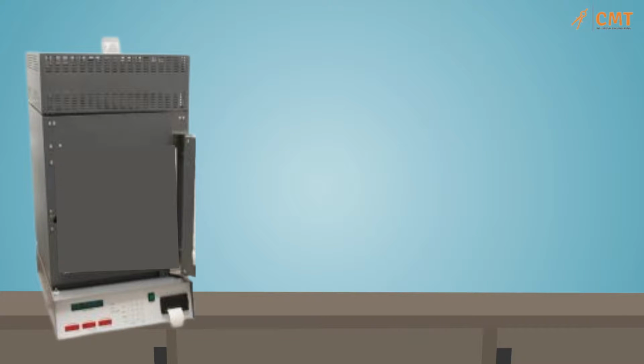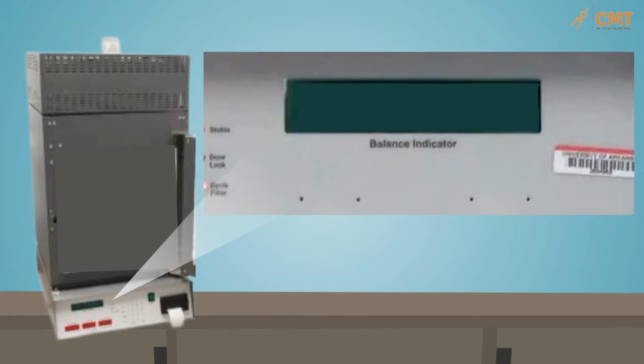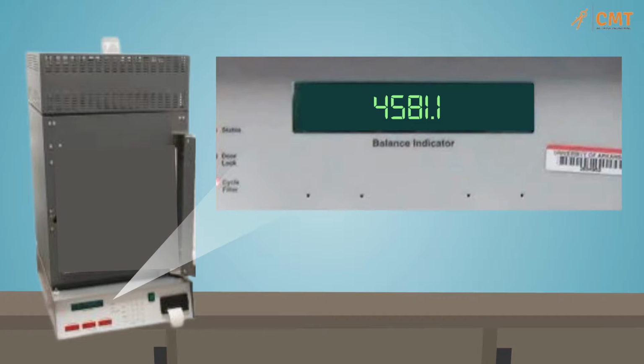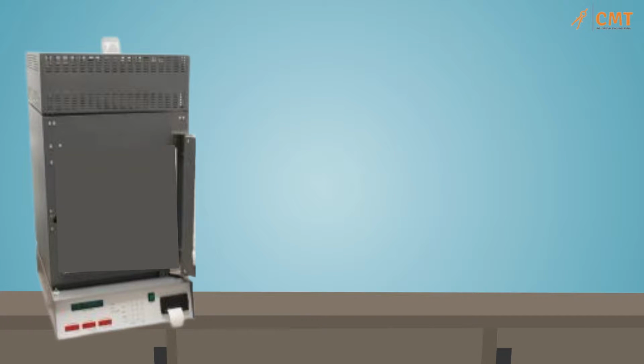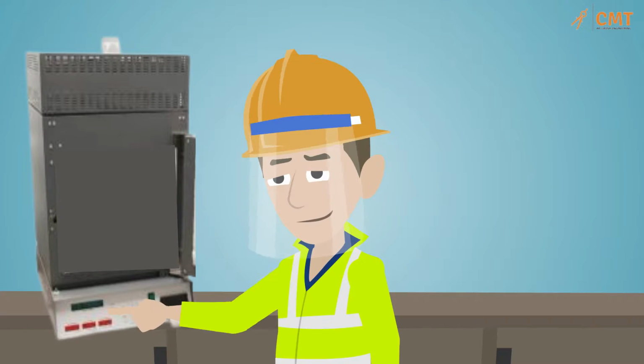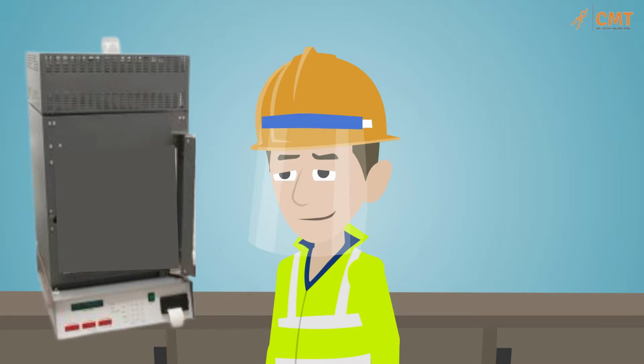Next, you will need to verify that the total mass of the basket assembly and sample shown on the oven display is within 5 grams of the total mass recorded from the external scale. If not, you will need to reposition the basket assembly to eliminate rubbing or check the scale calibration. Once the total mass is verified, you will need to start the ignition oven burn sequence by pressing the start button. The scale will zero out and the asphalt coatings will begin burning off the aggregate.